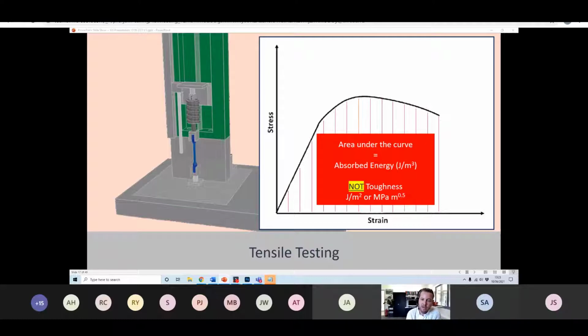So this area underneath that curve, this total area, cannot be considered to be a true measure of the material's toughness. Unlike ductility, though, it's not totally meaningless. If we can see that the area underneath that curve is large, then that does imply that a material will be tougher. Okay, so there is a correlation in this instance between this area and the real toughness of the material, but it fundamentally isn't the toughness that is being measured here, and it's really worth clearing that up again because, as with ductility, it's related to failure and fracture of the material. So it's really important that we understand these differences and these nuances.